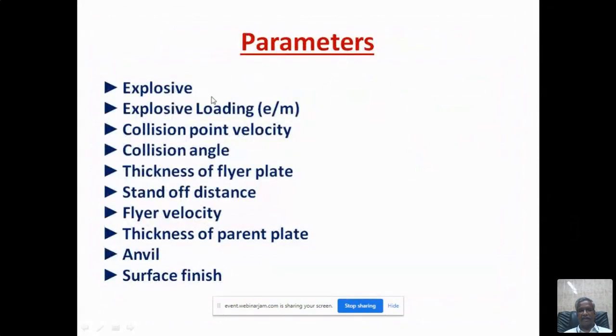And there are many parameters to control. So type of explosive, what explosive you are using, low explosive, medium explosive, high explosive, that depends on the detonation velocity. And explosive loading, which I told you, E by M, the mass of the explosive to the mass of the flyer plate, and collision point velocity, collision angle, 30 degrees, 45 degrees, 60 degrees, and thickness of the flyer plate, and the standoff distance, how much standoff distance you are keeping, whether you are keeping 1 mm or 1.5 mm or 2 mm. And then flyer velocity, thickness of parent plate, that will also play. And anvil and surface finish, they all will play. But majority, this explosive, types of explosive loading and the collision angle, flyer plate thickness, standoff distance, these 5 parameters will play a predominant role on the explosive cladding than the other parameters.